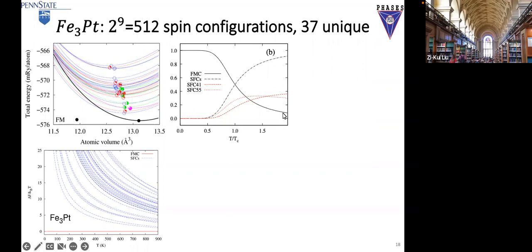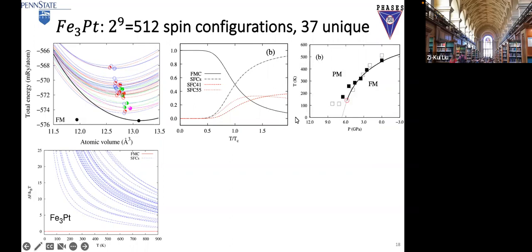So now each of these configurations has properties, right? They're predicted from DFT. So we can calculate the phase diagram. The symbols again are from experiments. The line is from the prediction. It's purely a prediction from DFT. And the red circle here is very important. It is a critical point. A critical point is where you have divergence of the properties, the singularity.